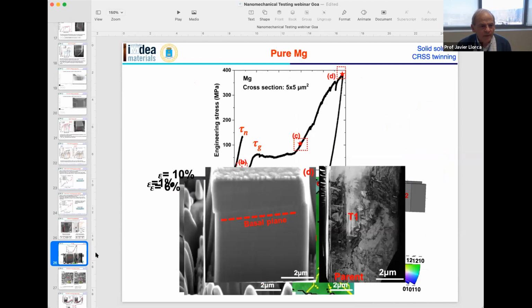So let's go here, and I guess I need to activate the play, at least for some time, for the sake of clarity. This is the typical result that you get of the engineering stress and engineering strain curve of one crystal that is oriented for twinning. You have an initial linear region, then you have a pop-in, the load goes to 0, which means some phenomenon has occurred, that you will see is twin nucleation. Then as you deform more, the punch gets in contact with the micropillar, and you have a region with practically constant deformation, or deformation at constant stress, and then you have a strong hardening.